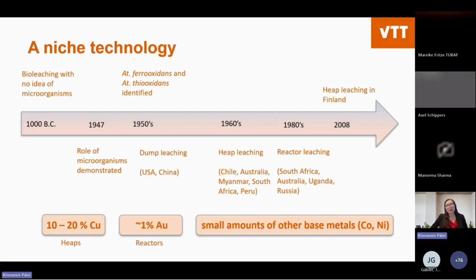The first bioleaching operations were dump leaching, later heap leaching. In the 1980s, it went forward to reactor leaching. I mention here specifically the heap leaching in Finland, because it was the one taking place in Europe. And this means that the different bioleaching technologies are commercially used worldwide. There have also been estimations of how big a portion of different metals is produced using bioleaching. The estimate is that about 10 to 20% of copper is produced globally using bioleaching, perhaps about 1% of gold, and small amounts of other base metals such as cobalt and nickel are mentioned as well.